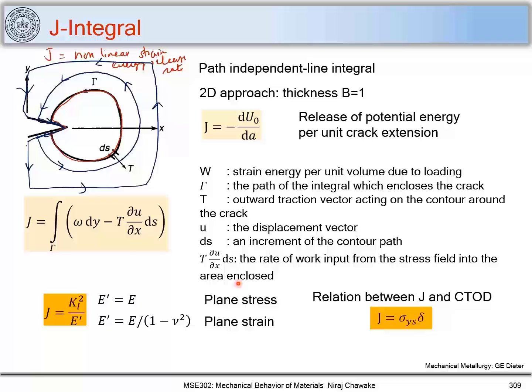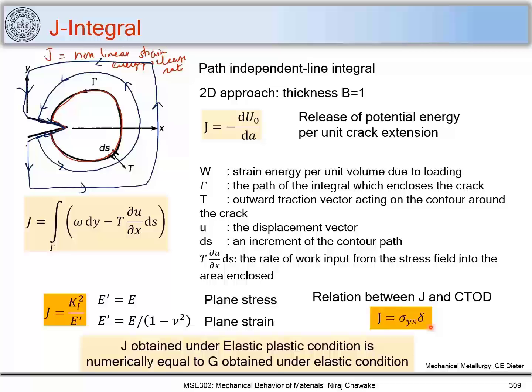You can refer to any standard textbook to find out how to do this integration. Let's say you can just use this reference, Mechanical Metallurgy by George Dieter, and you can see for yourself that J has this value. Now, in earlier slides, we have seen that J is equal to sigma ys into delta, and what does it indicate? So it gives you a most important understanding in fracture mechanics that J obtained under elastic plastic condition is numerically equal to G obtained under elastic condition.